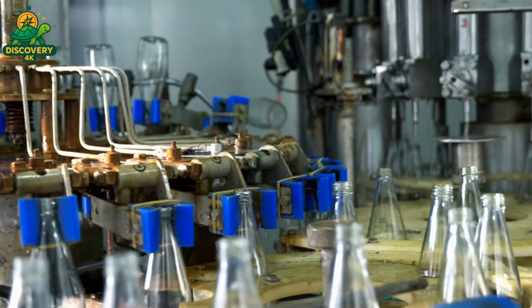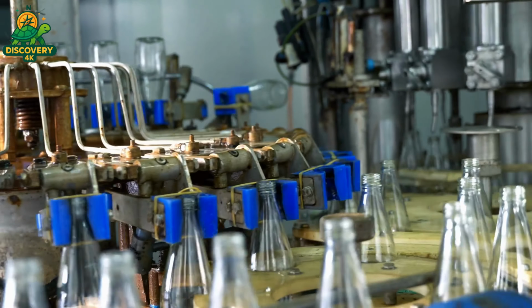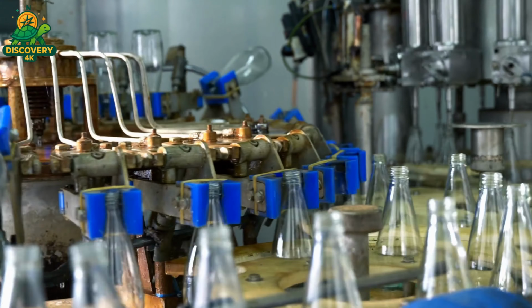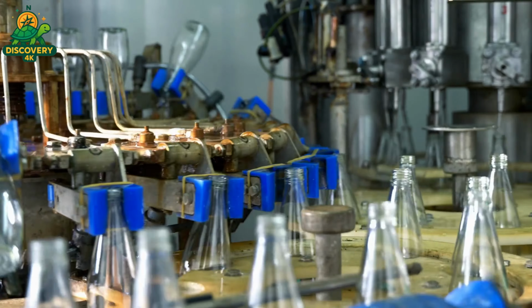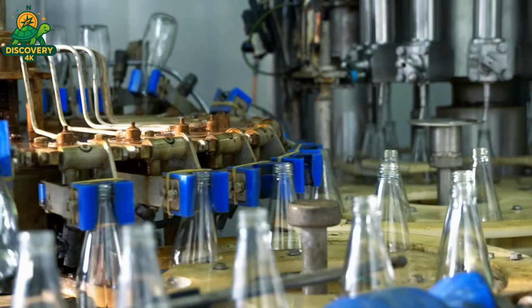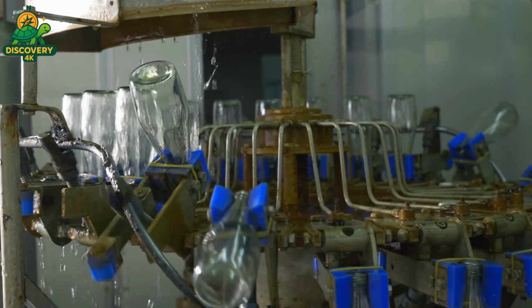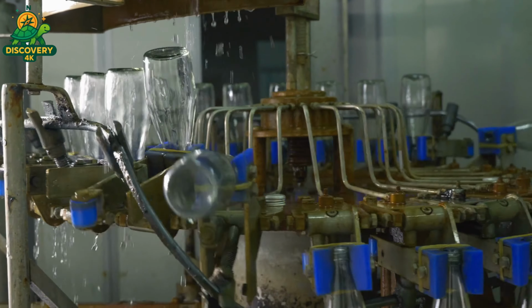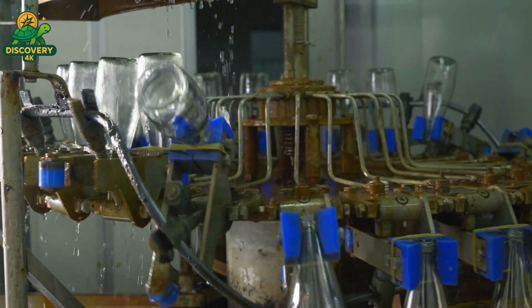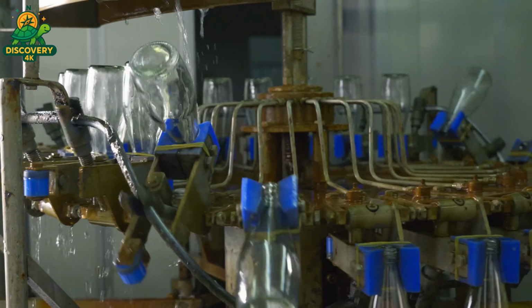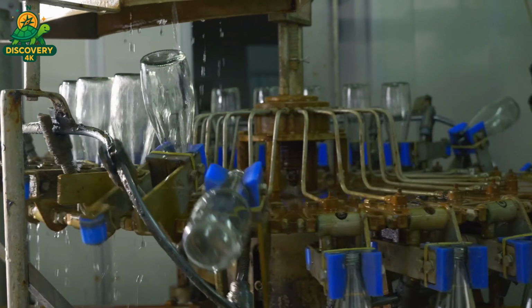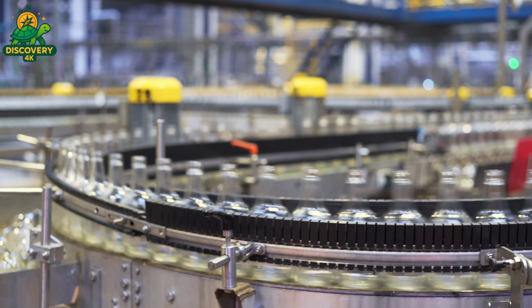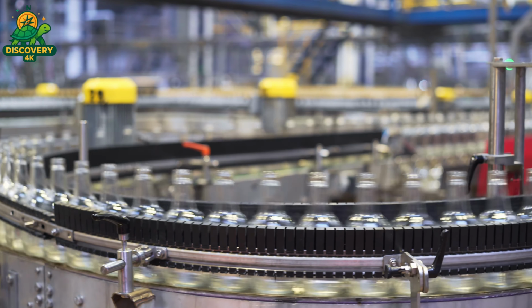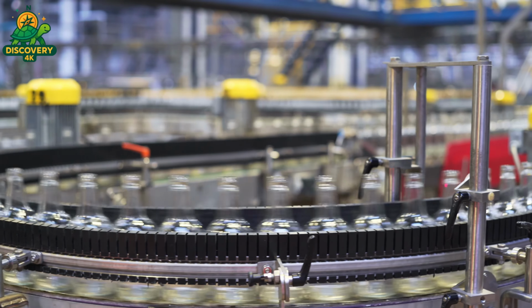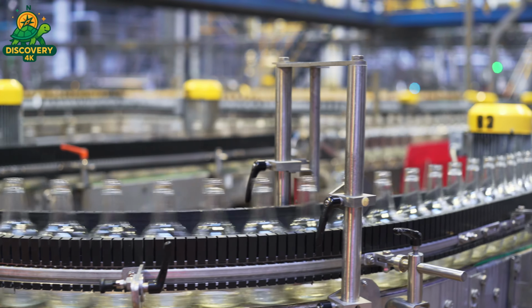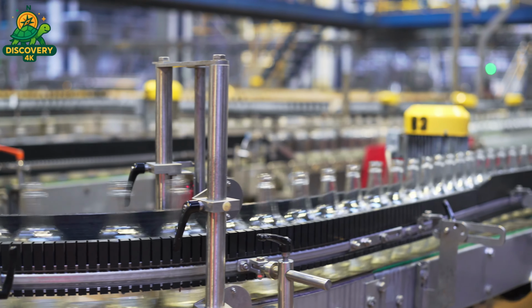As bottles exit the annealing lehr, they pass through a high-speed inspection system. Here they face a barrage of tests, both automated and manual. Visual inspection cameras and sensors scan each bottle at incredible speed, checking for cracks or fractures, air bubbles trapped in the walls, inclusions, foreign particles embedded in the glass, irregular shapes or dimensions. Defective bottles are instantly rejected and sent for recycling.